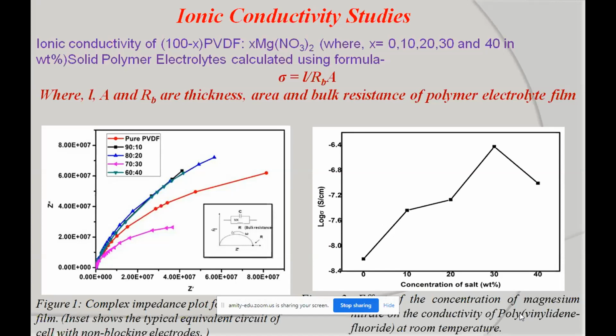Figure one represents the complex impedance plot for solid polymer electrolyte cells for our compositions, and the inset shows a typical equivalent circuit of the cell with non-blocking electrodes. And figure two represents the concentration dependence of our salt at room temperature. From figures one and two, we got the highest conductivity value for 30 weight percent of MgNO3 in polyvinylidene fluoride.